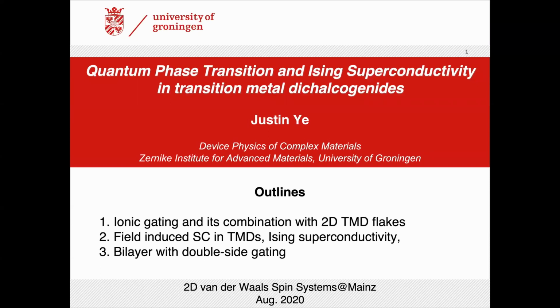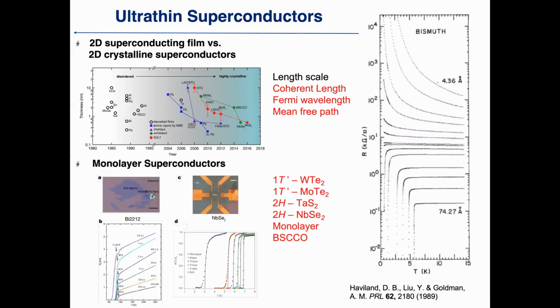The general motivation about this work is about making ultra-thin superconductors. So there are many works about thin superconductivity. The general point is that if you make a superconducting thin film, the requirement is actually not very high, because you are limited by the parameter called coherence length, which is normally very long in the metallic system. So if you make a thin film of a few tens of nanometers, then you are in the 2D regime. Then you can talk about the ultra-thin superconductor in the 2D limit.